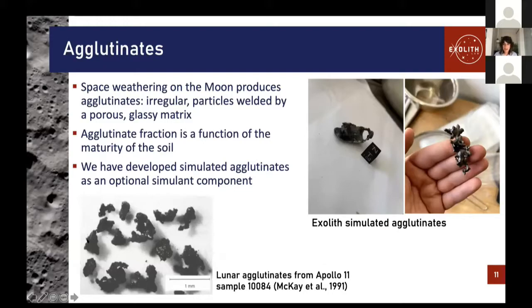And so I mentioned this, here's the other thing that we're working on, which is an agglutinate simulant. So agglutinates are these irregularly shaped, very interesting particles found in the lunar regolith that are made of lunar regolith, but they're welded together in a porous, glassy matrix. And these particles are formed by space weathering processes, especially bombardment of micrometeorites. And the percentage of agglutinates in the lunar soil is a function of how mature that soil is. So the longer it's been weathered, the more agglutinates you'll have.